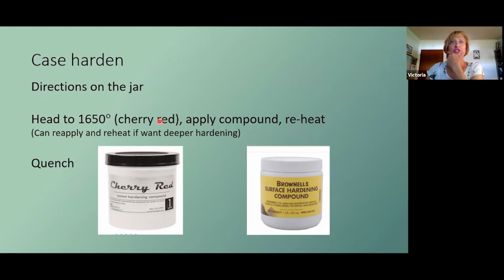And it's a good idea to read the directions before you do this, or maybe even review it with your local instructor. But in a nutshell, you're going to heat it to the transformation temperature, which is austenitic. And we need that to get to martensite, which makes the tool hard. So with your tool in that austenitic temperature, which means 1650, it's going to be a cherry red color. It will have lost its magnetic properties at that time.